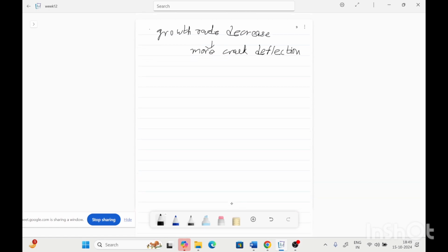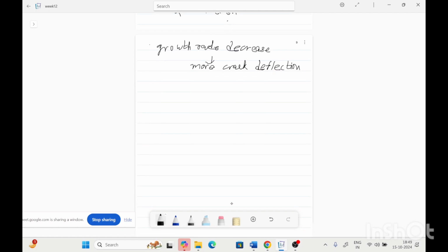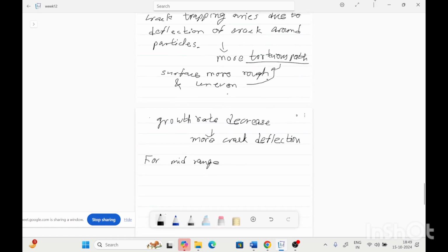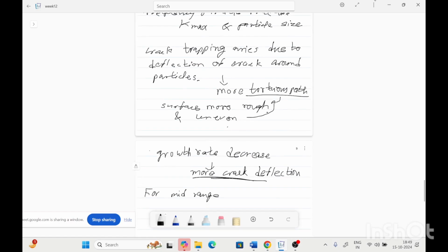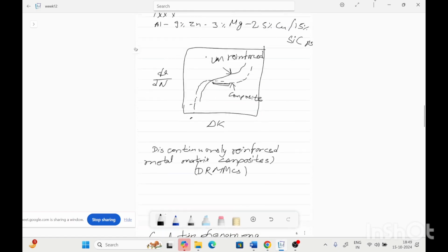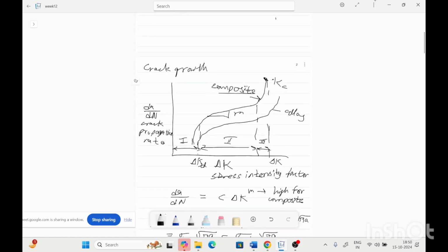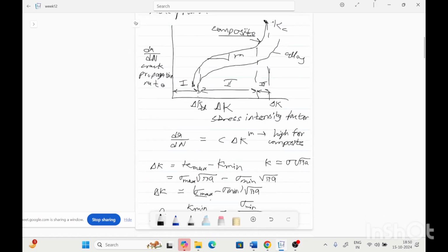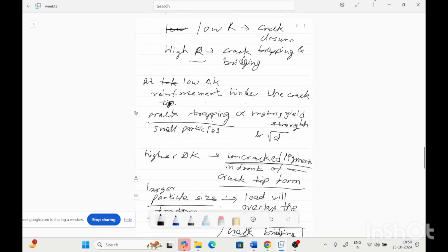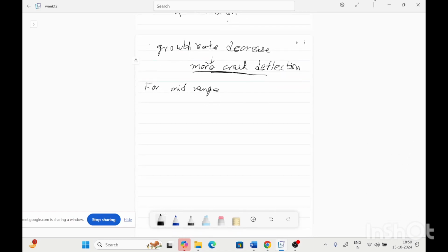So this is for the lower crack growth rates, means here crack growth rates are low. Sorry, the low corresponds to the stage 1 crack propagation. Means here in this region, the initial crack propagation will depend on all these, crack branching, crack deflection. And for the mid-range growth rates, we are considering the stage 2 region, means the Paris region.